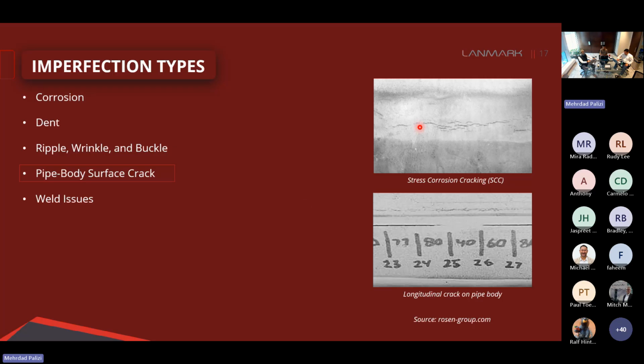So if we take a look at this picture, we have a group of cracks aligned in the longitudinal direction. And perpendicular to that, we have hoop stress that is acting as the driving force. Cracks can also grow by fatigue. This is going to be over the critical locations that we have stress concentration. There is higher levels of stress and strain at this location, and during pressure cycling, cracks can develop and grow over time.